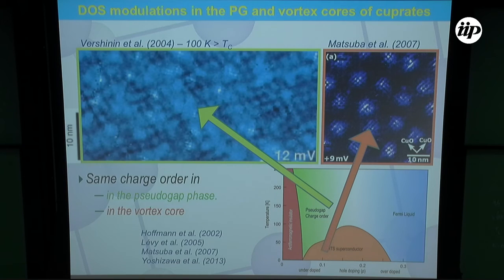So the last remark is that we know now that these bound states, these subgap states, are not specific to the vortex cores. But we don't really know where they are coming from. We know they are uniformly spread over the surface. We measure them with a constant intensity. And it's quite tempting to link these states with the charge order, which has been discovered not so long ago in the cuprates. This is the example of BISCO vortex cores, clearly seen. And you see that in each of these cores, there is a modulation, a pattern, which is actually 4 by 4 unit cells. It's the same kind of modulation which is seen above TC in the pseudo-gap regime.